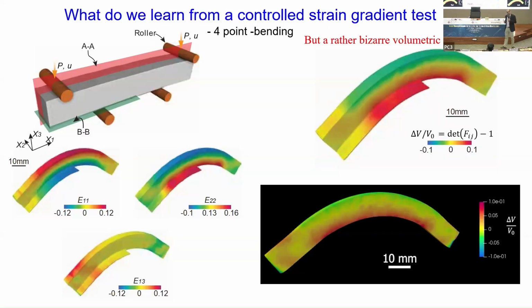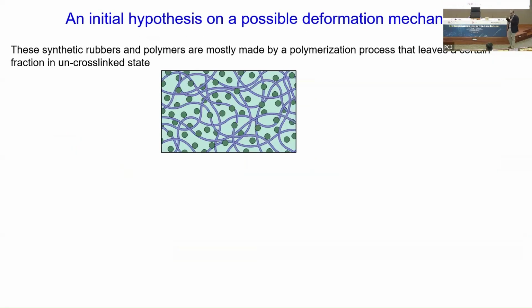And so this is the sort of thing that happened in this project. We started off saying that we're going to get data by which we're going to develop these models, and then we realized that our starting physical assumptions are wrong. So at this point, you have to start to hypothesize what are all the possibilities of the different kinds of physical ideas that are going wrong. Now, the first thing you realize when you think about it from a thermodynamic perspective is, how can you get a negative bulk modulus? Well, you can't really get a negative bulk modulus. But the idea of a negative bulk modulus is only happening because you have said that the stress only depends on strain and nothing else. If you say to yourself that the stress depends on strain and some other internal variable, then thermodynamically something else is happening. So the question is, is there any possibility of another state variable effectively existing for this rubber rather than just strain? Now, you have to remember how you make silicone rubber.